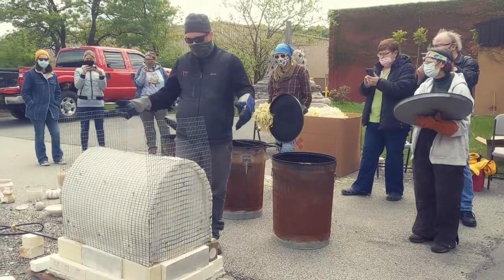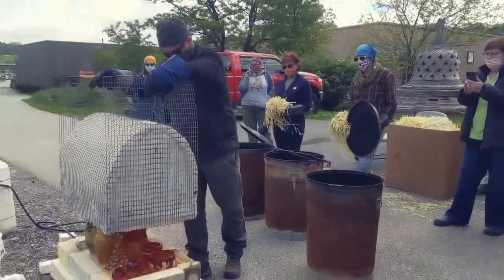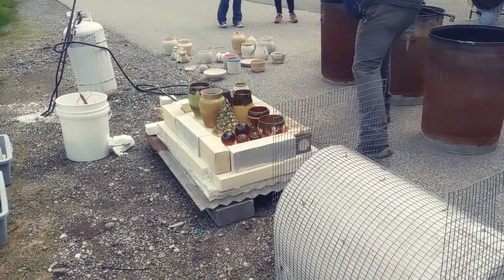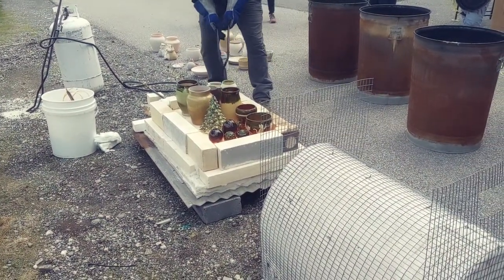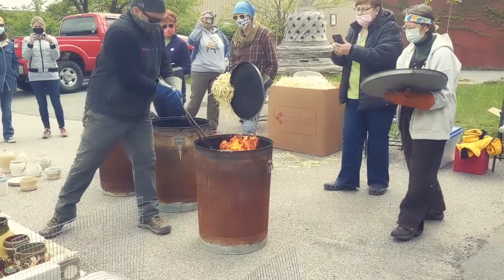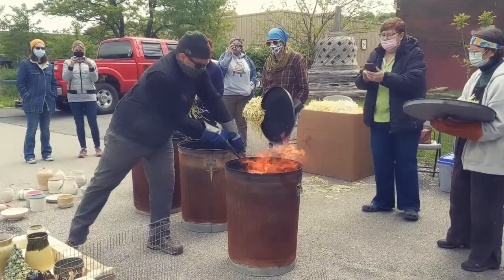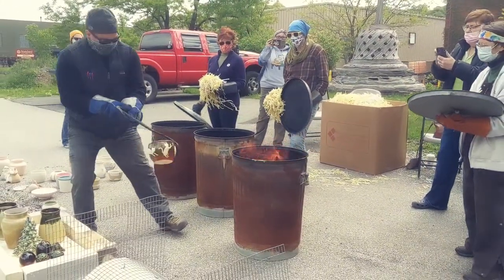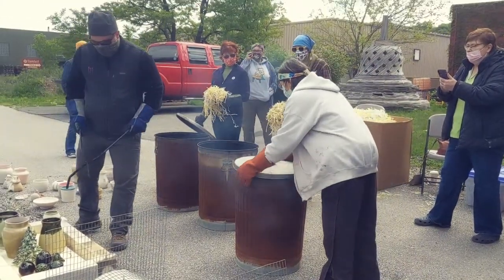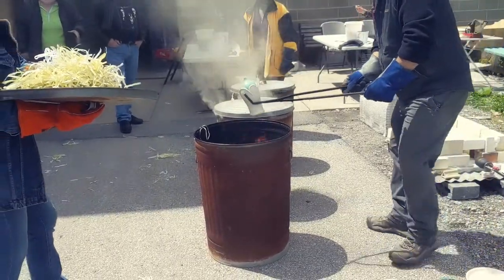He's using the technology but also peeking in as things get hot. What he's going to do now is lift the top of the kiln off so that it exposes the pieces, and then take each piece with a pair of blacksmith tongs and put them into the combustible materials. He doesn't want the potter on the outside to close off the lid until he has all the pieces in. Sometimes he's going to ask for more people to put paper over top so that there is more carbon burn-off to create that surface. Sherry closed the lid with paper on the inside so that all of that paper would burn up inside the vacuum.